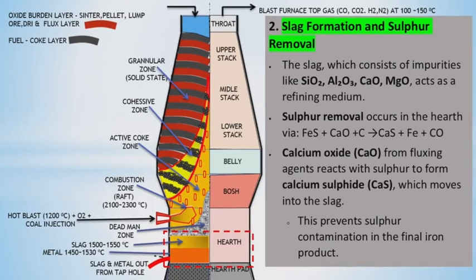Slag formation and sulfur removal. The slag, which consists of impurities like silicon dioxide, alumina, calcium oxide, and magnesium oxide, acts as a refining medium. Sulfur removal occurs in the hearth via FeS + CaO + C = CaS + Fe + CO. Calcium oxide, CaO, from fluxing agents reacts with sulfur to form calcium sulfide, CaS, which moves into the slag. This prevents sulfur contamination in the final iron product.